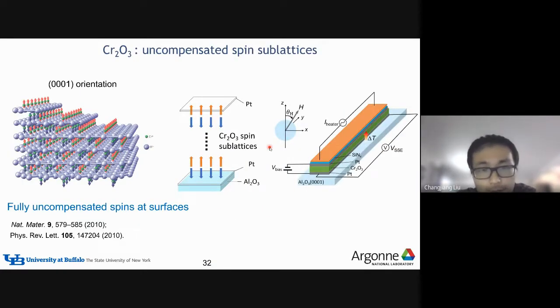So the material we were interested in is the chromium oxide, or chromium two-three, Cr2O3. So just to remind you, this is a classical antiferromagnet. In particular, when this material is grown along the 0001 orientation, the two sublattice magnetizations will be pointing up and down, and they actually can form an uncompensated surface. This is because these two sublattices are grown